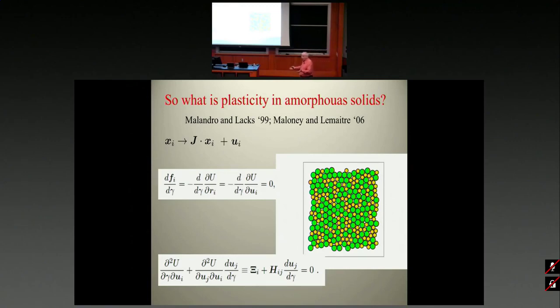If I do a small one, the non-affine is going to be small. If I make a large strain, the non-affine is going to be large. So I have a dependence of ui. So I now can get the chain rule and say that the second contribution is due to the dependence of ui. So I get the discrete du duj dui dotted into duj d gamma. So here are the contributions to the dependence of u on gamma. Now, this is a very well-known matrix. It's the Hessian Matrix, Hij, that I'm going to use in a moment. Here is a vector because it has only one index, so let's call it xi i. It's known in the literature as the non-affine force, and now all this thing has to be zero.